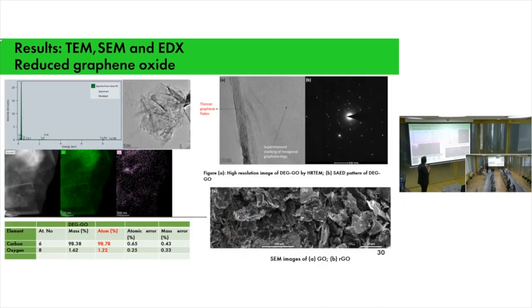But after you reduce the graphene oxide, you see that the carbon ratio increases significantly to almost 99% with oxygen at 1.22%. And here, after you reduce the graphene oxide filler, you see thinner graphene flakes with superimposed stacking of hexagonal graphene rings. And then after the reduction, our graphene exhibited some crystalline structure, which is very pertinent when you're dealing with the thermal conductivity of a composite system. Moreover, in the SEM images, there is a big difference between the reduced and graphene oxide filler.